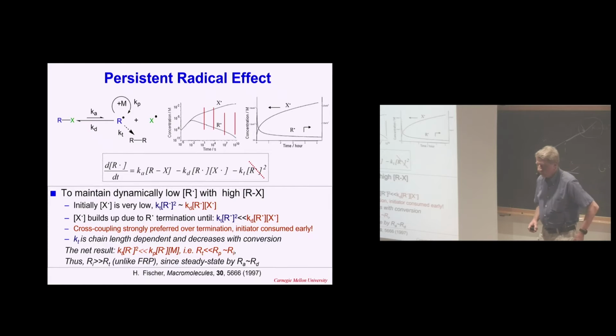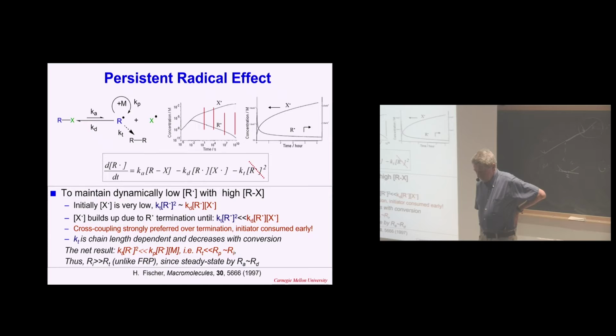So you said that all of the polymers change the gradient at the same time. Don't we have a low concentration of radicals? Yes, but you have a large population. Concentration of radicals in conventional and in controlled process may be the same. But fraction of terminated chains in conventional is 100%. Nearly all of them are terminated, except this tiny amount of them which propagate.